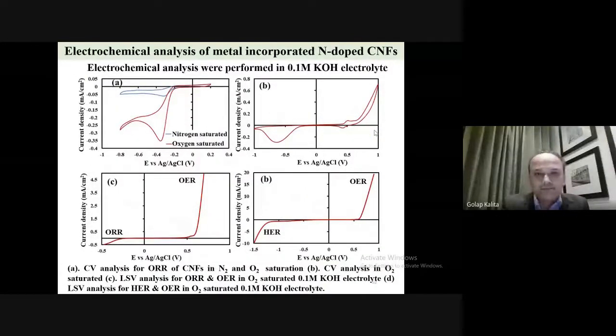This type of material we also tested in 0.1 molar KOH solution, which is 0.1 molar KOH in water. Then we do the CV analysis in nitrogen-saturated and oxygen-saturated conditions. If you have oxygen saturation, we get very good ORR activity, the oxygen reduction reaction. We also do CV analysis in a wider voltage range from 1 to -1 volt. This is the ORR, and here is the OER activity, so it's bifunctional activity.